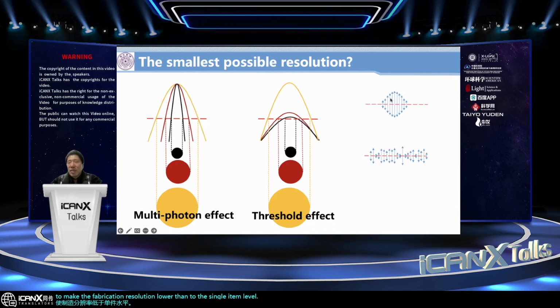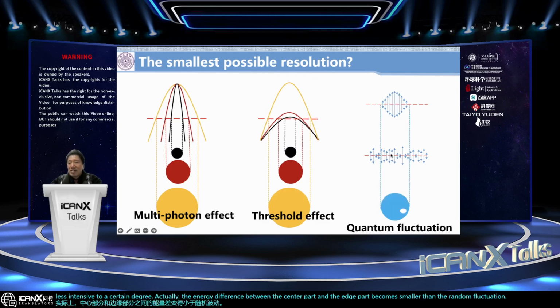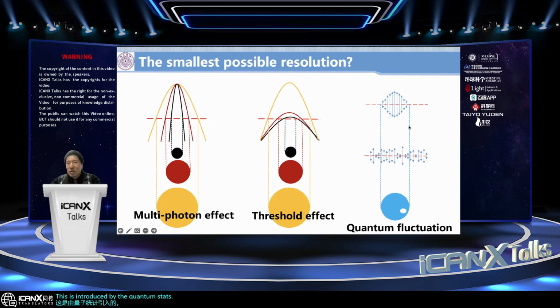The reason is when we reduce the light intensity to a certain degree, actually the energy difference between the center part and the edge part becomes smaller than the random fluctuation energy. Actually, this is introduced by the quantum statistical effect. So it means when we reduce the focus spot to a certain smaller area in laser fabrication, the damage will occur inside the area, but in which atoms we don't know.